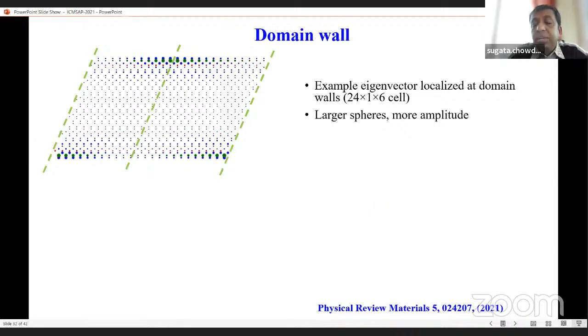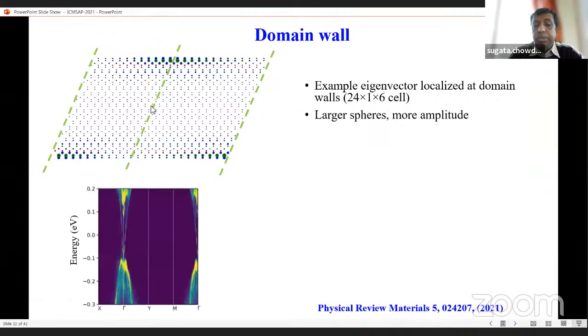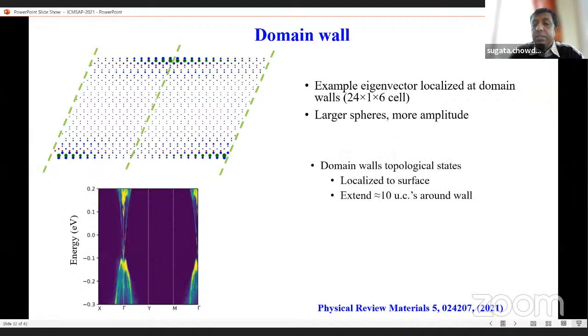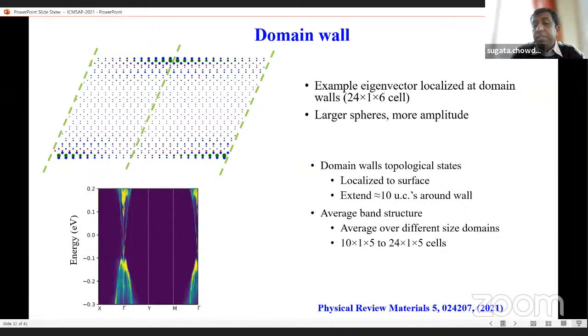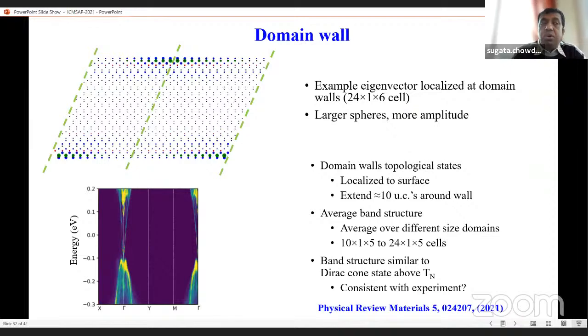And then we developed a magnetic domain model. So these are the different magnetic domain walls we created, and we noticed that this kind of topological state is localized. And when it is localized, that means when you are doing the experiment, which domain you are probing is the most important part in these cases. The domain wall means the largest effect. It is telling us that the magnetic property depends on the magnetic domain walls inside the system.